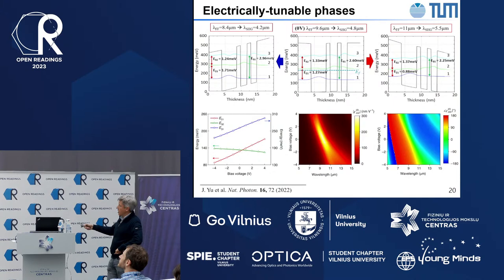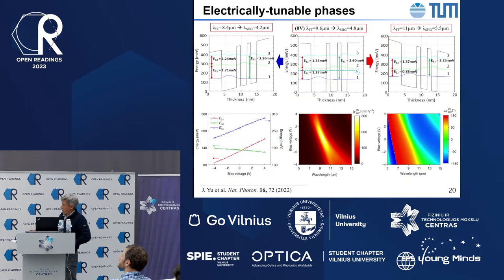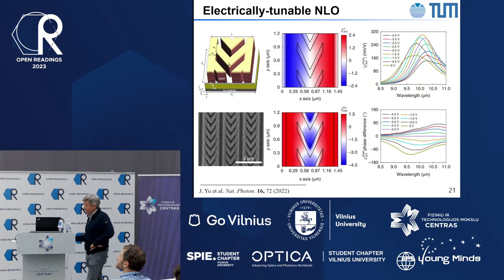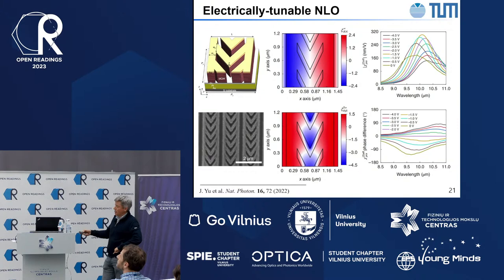And so this is how energy levels of these different states change, and these are the results of simulations to predict how the amplitude and the phase of the nonlinear response will change. And now we can fabricate these metasurfaces. Now the antennas are a bit different. They're all connected because we want to bias this entire structure, so everything has to be continuous, covered by some continuum of gold. So the antenna design is slightly different, but the idea is similar. You have some local field enhancement, and you compute the overlap integral.